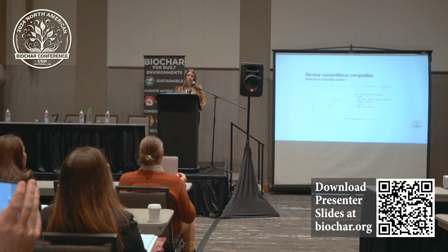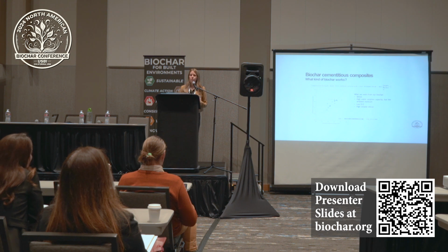So really, given that this is such a big predictor of the strength, what that tells us is that one of the main ways that biochar is affecting the strength of cementitious composites is through a reduced water-cement ratio, something called an internal curing agent is what it's acting as. So basically what that means is that you're mixing everything in with water. Depending on how dilute your concrete system is, it's pretty predictive of what the final strengths will be. It basically gives you an indicator of how many pores will be left in the concrete once it hardens. Now, if you can throw in an internal curing agent, you're taking out some of that water that gets released again for additional reaction later, and you get a stronger composite. So that number is really indicating that that's one of the big roles that biochar plays. And so we want to try to maximize that impact.